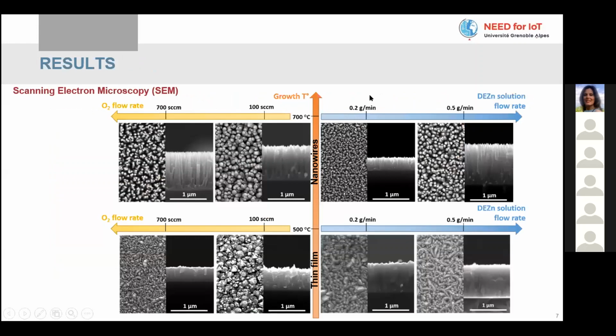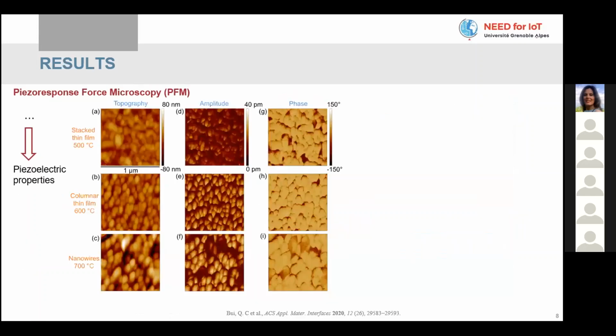So here for some results, we see that when I grow the zinc oxide at different temperatures, at 500 we get the zinc oxide with the thin film structure, and at 700 we have the nanowire structure. And we also see that by varying other parameters like oxygen flow rate and diethyl zinc flow rate, the thin film morphology changes, and also the dimensions like the diameter and the length of the nanowire change with these parameters. So we see that different parameters can affect the structure, and this will also affect the electrical property of the zinc oxide. And these two lead to the changing of the piezo property.